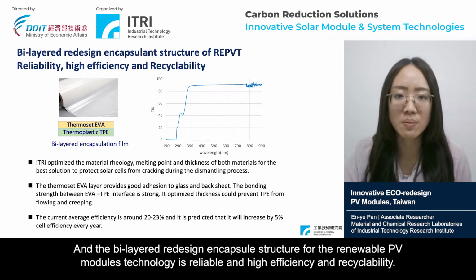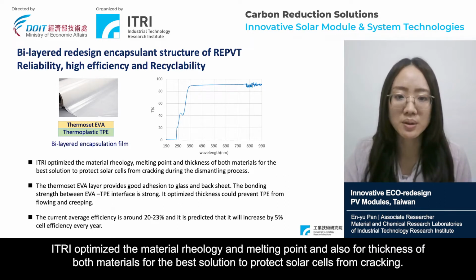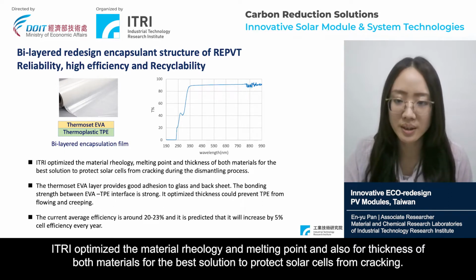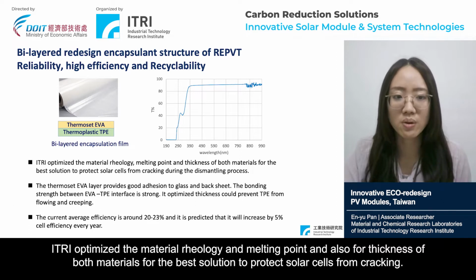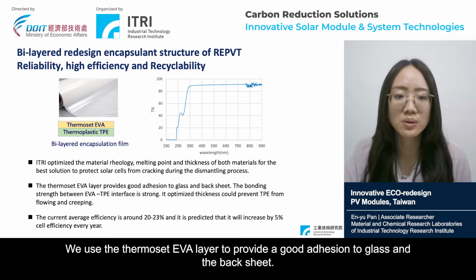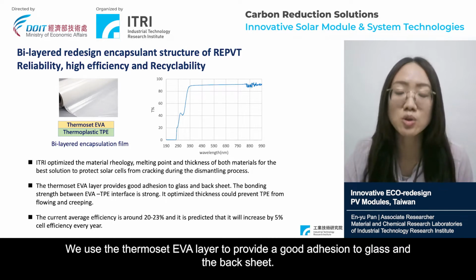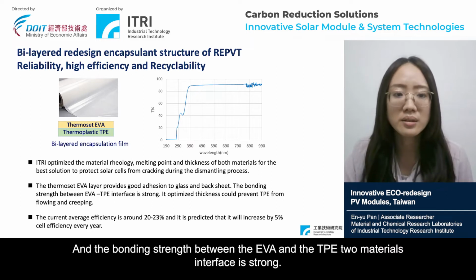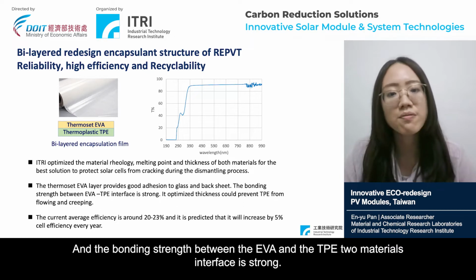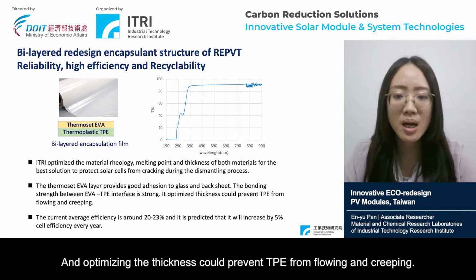The bilayer redesigned encapsulation structure for the renewable PV module technology is reliable, with high efficiency and recyclability. It requires optimizing the material rheology, the melting point, and the thickness of both materials for the best solution to protect the solar cell from cracking. We use the thermoset EVA layer to provide good adhesion to the glass and the backsheet. The bonding strength at the interface between the EVA and the TPE is strong, and we optimize the thickness to prevent the TPE from flowing and creeping.